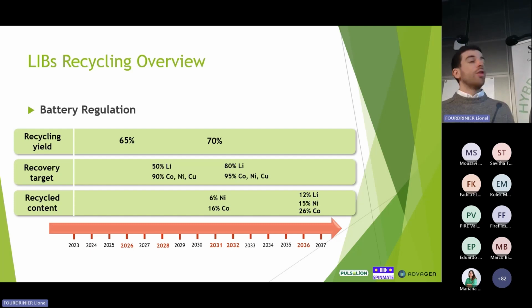Then there are also targets for the recovery of specific materials, which are the lithium, the cobalt, the nickel, and the copper. So the target by 2028 is recovery of at least 50% of the lithium and 90% of the cobalt, nickel, and copper. And then by 2032, 80% of lithium recovery and 95% of the rest of materials.